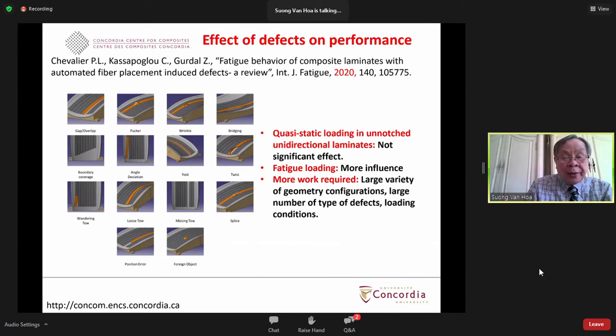So they also made a survey of the work that has been done on the effect of defects on performance. There have been quite a large number of papers published on this. From this survey, they found that for quasi-static loading in unnotched unidirectional laminates, the effect is not significant. The effect on the performance is probably less than 10%.